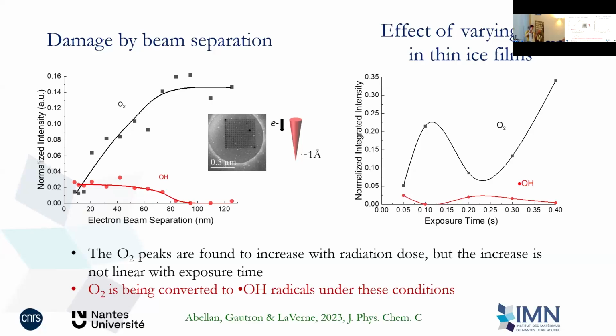So in the same conditions of irradiation, if you change the separation of a 2 Angstrom beam and you separate it 20 nanometers, they still see each other, because you keep separating and you keep changing the values of production in fresh new areas. Okay, you repeat this experiment in another fresh area, and I measure the thickness, so this is comparable. And you have to go all the way to 70 nanometers separation, 80 nanometers for these things to not see each other in these specific radiation conditions. It could be different.